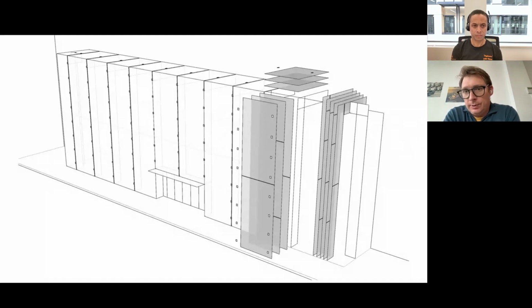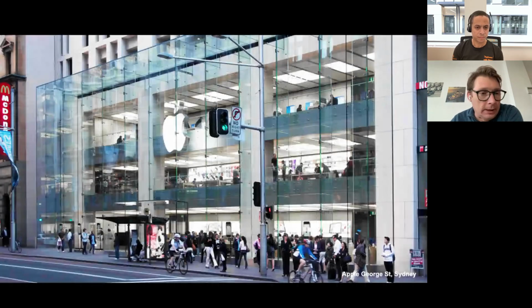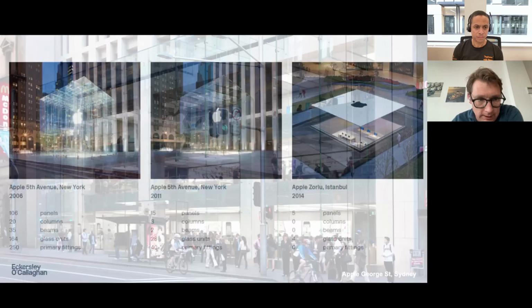this was increased to a 16 meter tall facade, because we could now procure glass in 8 meter lengths. And again, we're still cross-laminating the facade panels and the beams. But a big change that we had in Sydney was that we were further comfortable with the glass and the lamination acting as a shear component to transfer the loads between the glass plies. And it gives quite a clear appearance.